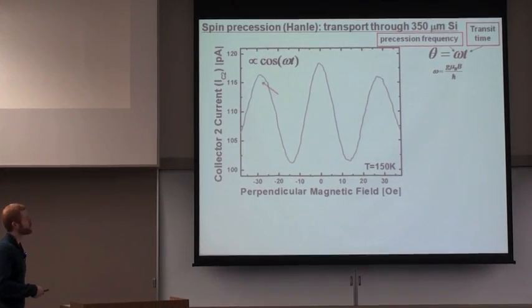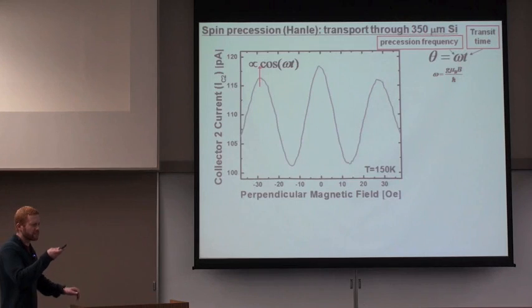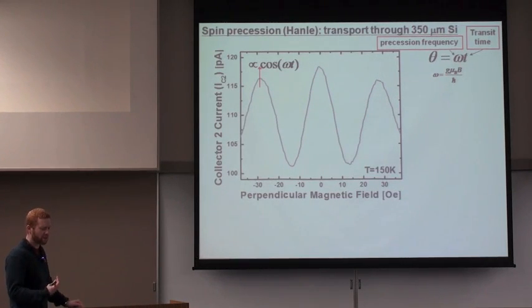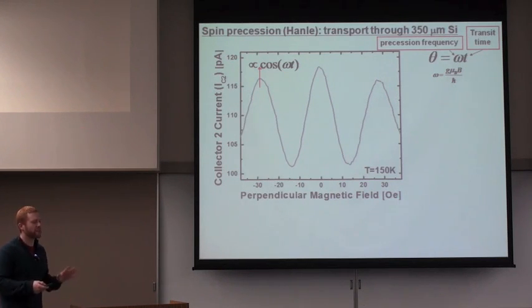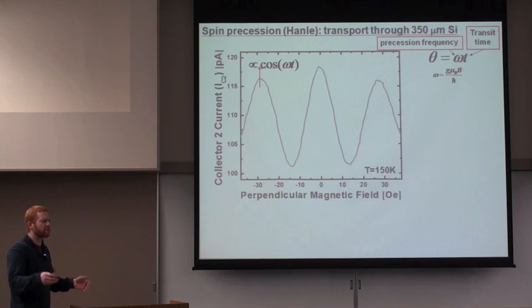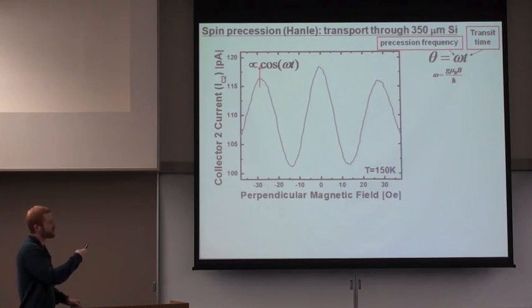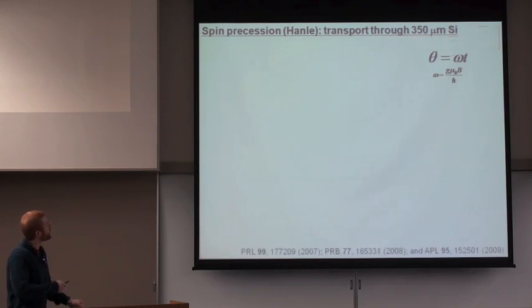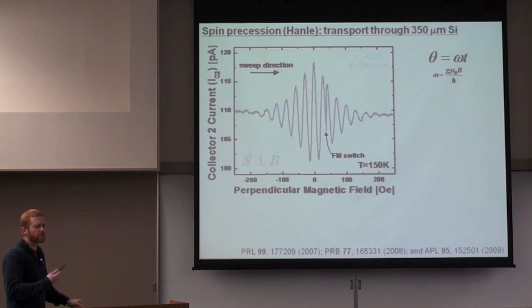Now, this process is periodic, and so, of course, if we just double the magnetic field, then spin up is injected. It precesses, but it precesses all the way back to spin up again, and so we recover our higher spin signal. Of course, what we would expect just based on this simple understanding is that we would get a signal which is proportional to the cosine of the precession angle. And so we would expect that we could just increase the magnetic field and we would get infinite orders of oscillation due to precession through multiples of 2 pi.